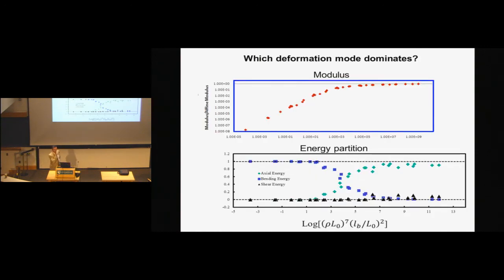Something else. How about the energy partition? That is, where do I store energy? How do these fibers deform when I'm in the affine range versus when I'm in the non-affine range? The plot here on top is actually the plot I showed you before in the previous slide. Modulus versus this parameter, which I described before. Okay? The lower plot actually shows partition of energy. Blue symbols correspond to energy stored in the bending modes of fibers, while the green symbols correspond to energy stored in the axial deformation modes of fibers.